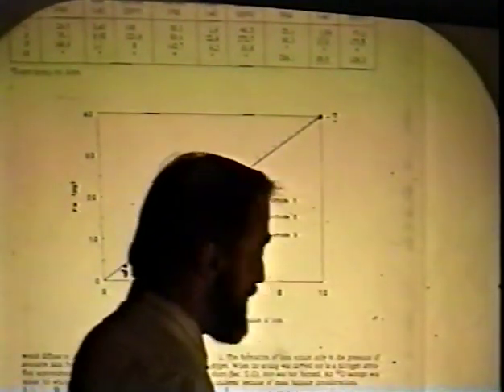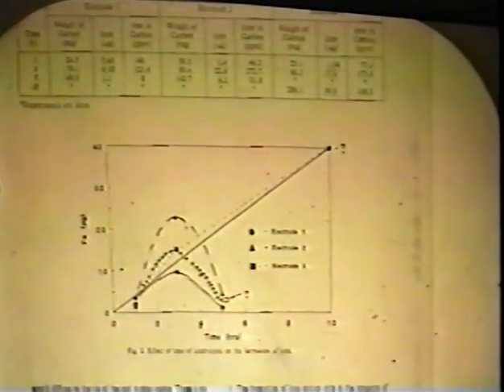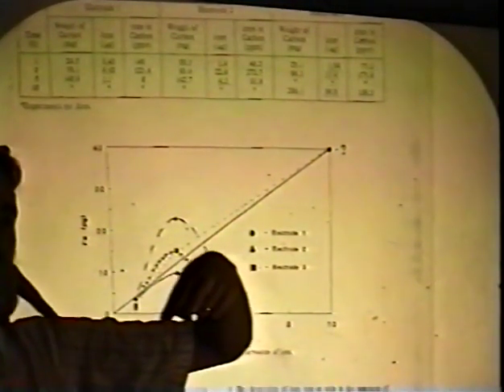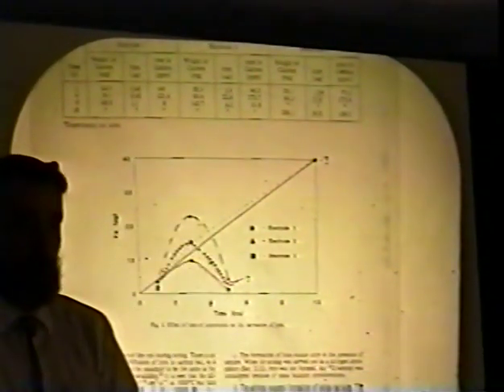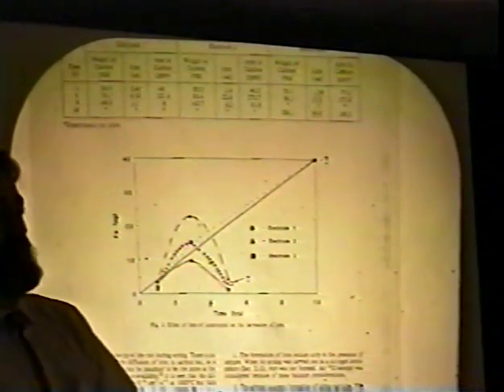Now, based on what we observed, I looked at a paper that Dr. Bacchus had done, in which they did a number of experiments versus time and pulled out a number of micrograms. This is the experiment where the carbon rods are in water and there's arcing between the carbon rods and the water. The material falls to the bottom. They analyze the material on the bottom and look at the micrograms of iron in the material at the bottom. And they had 3 sets of electrodes.